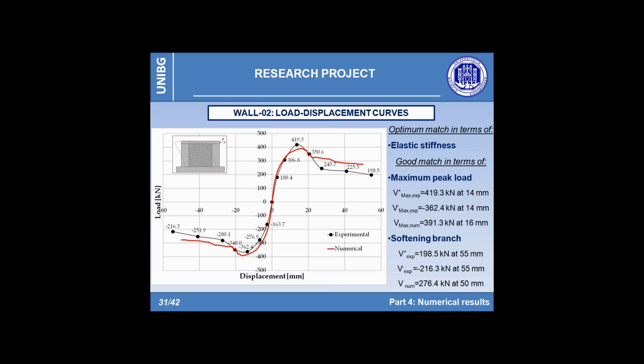Although the numerical analyses are not able to perfectly simulate the observed progressive strain degradation, the model appears efficient in synthesizing the structural response, giving a reliable indication of its bearing capacity, both in terms of ductility and of maximum residual strength.